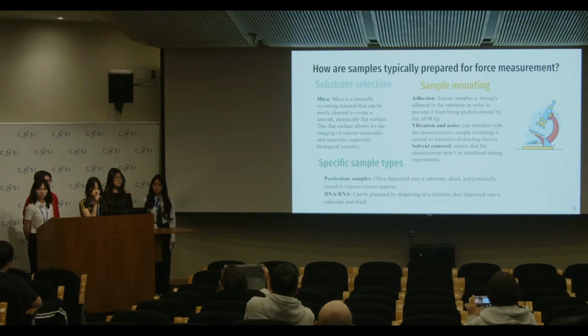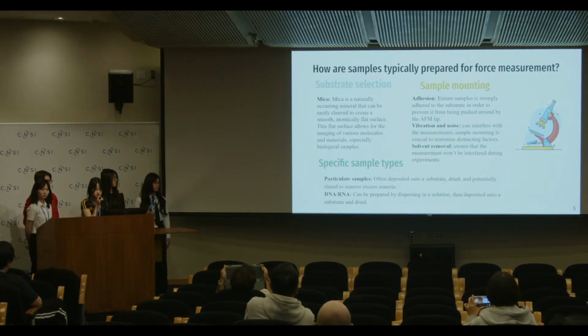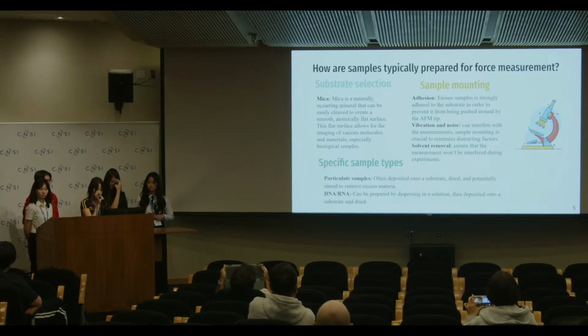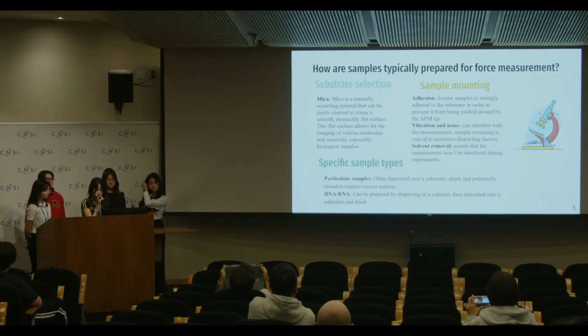Second, we have sample mounting. Adhesion ensures the sample is strongly adhered to the substrate in order to prevent it from being pushed around by the AFM tip. Vibration and noise can interfere with the measurements. Sample mounting is crucial to minimize distracting factors. Solvent removal ensures that the measurement won't be interfered with during experiments.